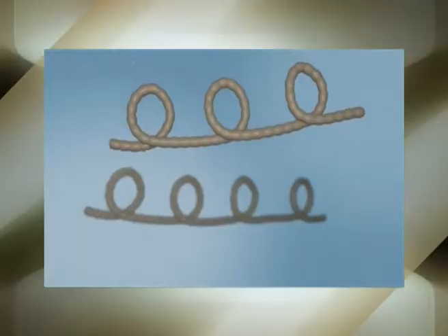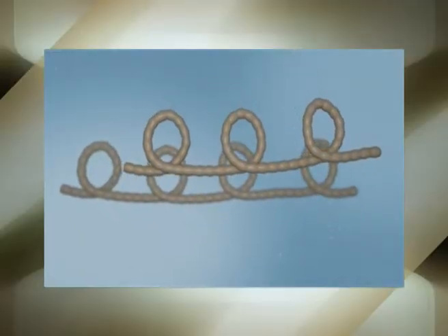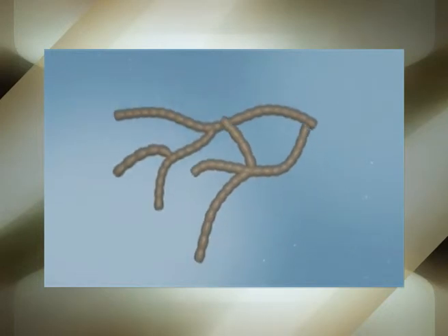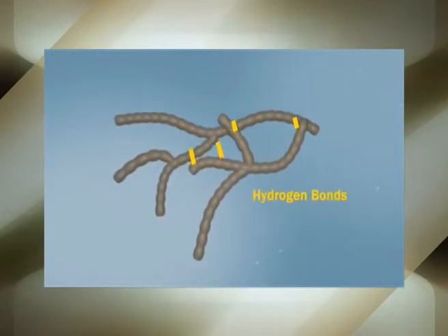The tendency towards retrogradation is enhanced at low temperatures, especially near 0 degrees Celsius, neutral pH values, high concentration, and by the absence of surface active agents. Retrogradation is also referred as setback and occurs with recrystallization of amylose. Amylose is much more susceptible to retrogradation, and amylopectin is only minimally involved in starch retrogradation, even though amylopectin has been shown to influence retrogradation and syneresis in cornstarch gels.